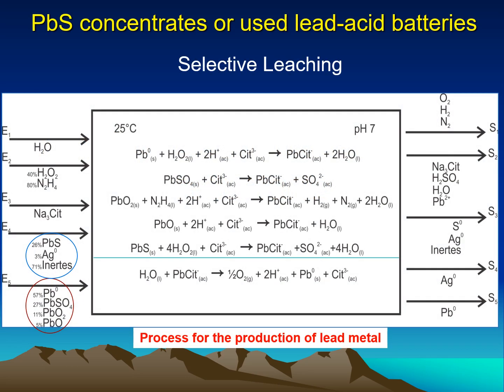Our first example is the obtention of lead metal from lead that's contained in galena concentrates or in used acid batteries by selective leaching at room temperature and pH 7 using sodium citrate solutions. The first four reactions that we see here are the reactions that take place when we're leaching a used lead acid battery. So we have lead metal or lead alloy, lead sulfate, lead oxide, and lead dioxide. As an oxidant, we'll use peroxide, and as a reducing agent, we'll use hydrazine hydrate.